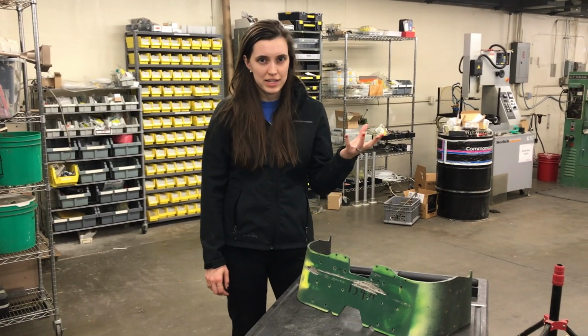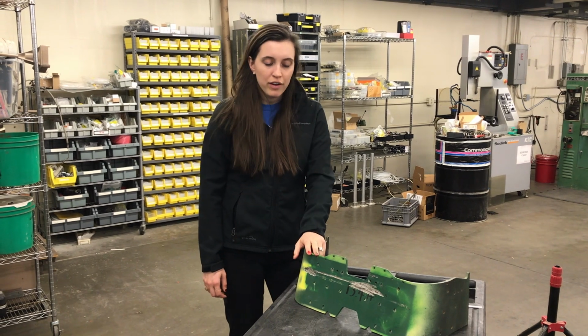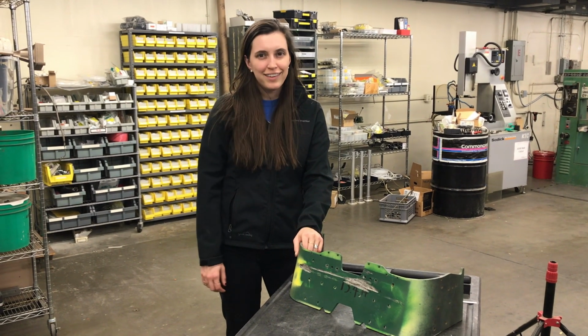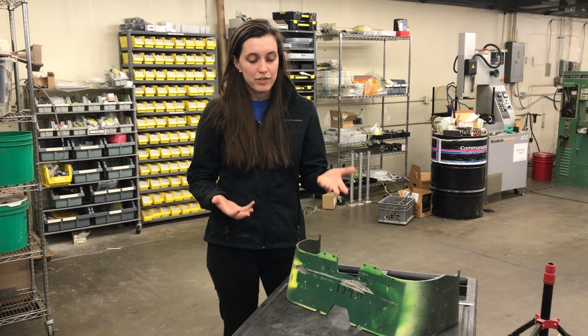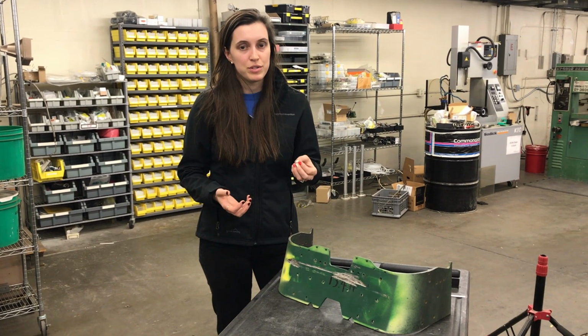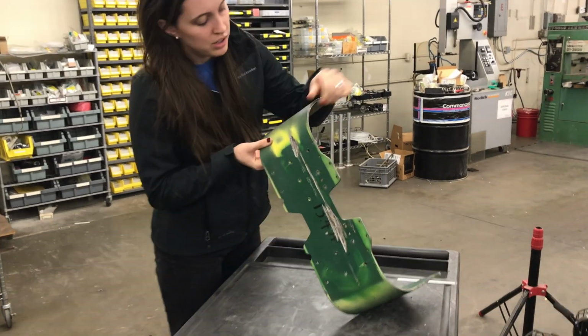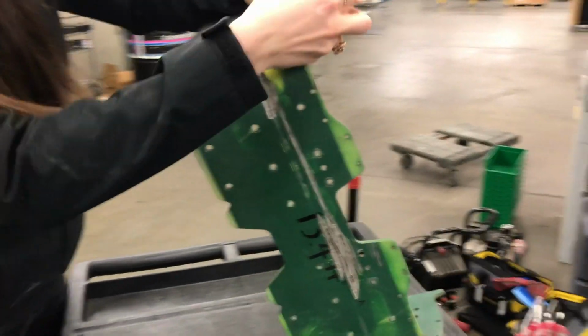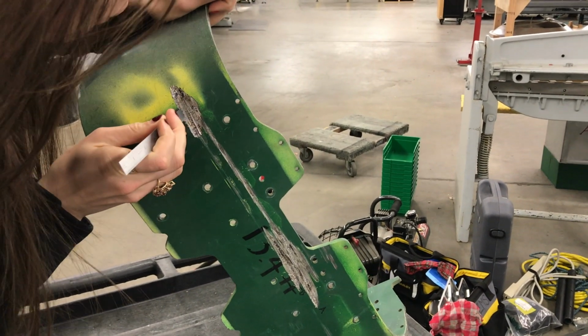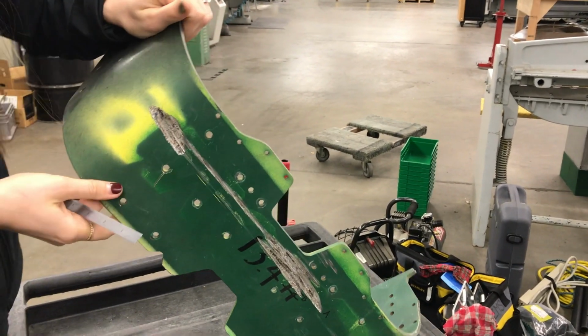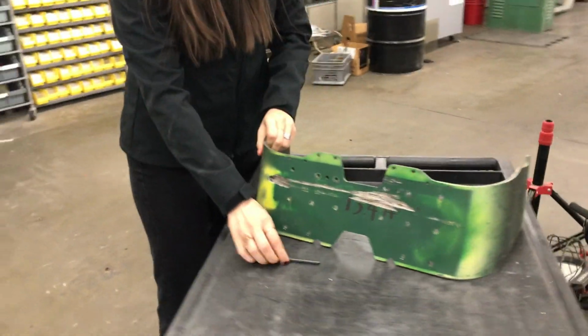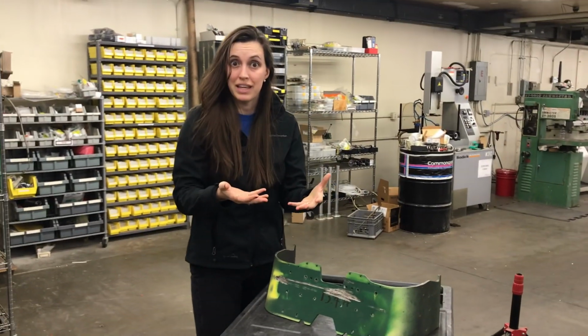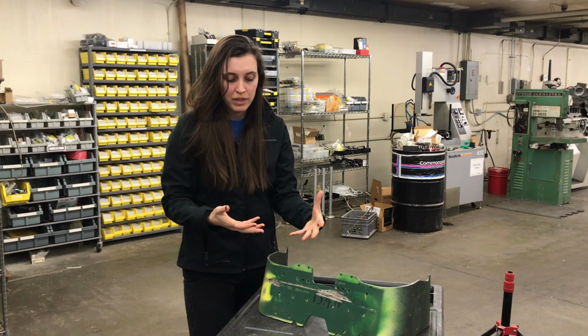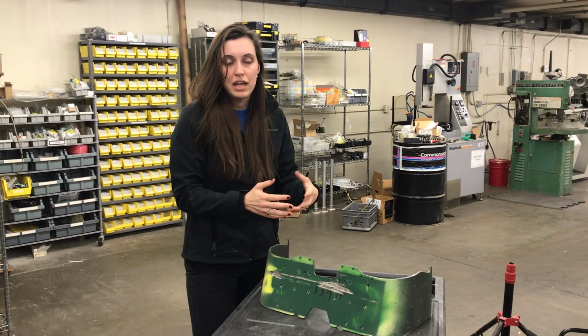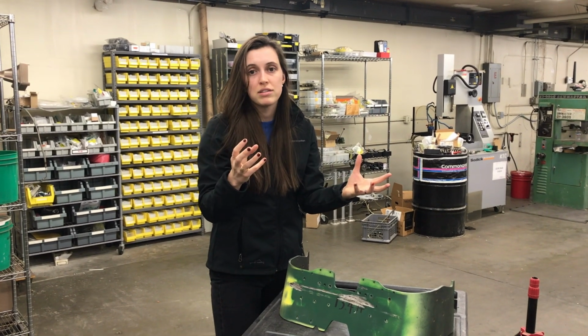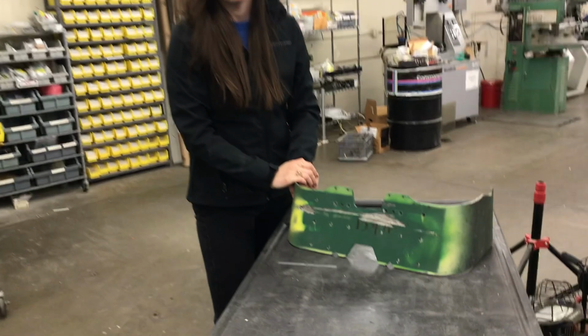If you've watched the other crate test videos, you might have seen the AR500 test and thought, huh, not very dramatic. That's because AR500 really is good armor, and we saw it do its job. If you look at the armor, it got maybe a 1/16 of bite at the most, but it was hard enough that it didn't let the S7 tool steel blade really bite in and impart a lot of energy. Instead, it skidded backwards and it made this dramatic shower of molten sparks, but other than that, it didn't really affect the bot that much.